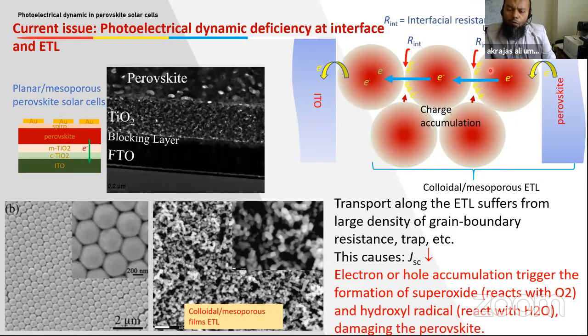This will induce charge recombination at this interface, and also induce recombination in this material, and also electrons that exist on the surface of this particle may react with oxygen molecules at the interface of the surface, which will produce superoxide, which then will induce phase instability in the perovskite, and this will damage our devices. So we have to obtain highly dynamic transport in this material. We need to improve the coupling between ETL and perovskite, and also between colloidal structures in this ETL structure. So we may expect better electron transport in this device.